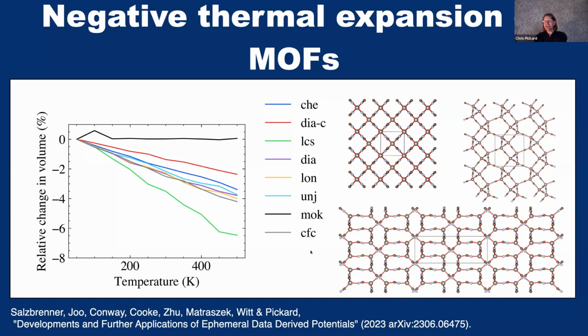And there's one experimental data point here for the diamond carbon. I don't think I've shown the actual numerical results here, but at around 300 Kelvin, the negative thermal expansion for Dia-C, which is an interpenetrating diamond structure, is known experimentally. And a little bit suspiciously, the value that he calculated was pretty much precisely what the experimental one was.